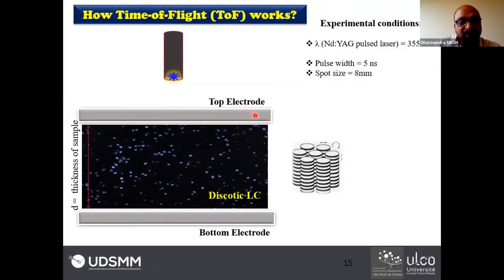Basically, what we do is place these discotic liquid crystals in between the top electrode and bottom electrode. In order to fix the thickness, we put in a spacer so that the thickness between the top electrode and bottom electrode is fixed. We fill this material at isotropic temperature with a very slow cooling rate, so that the molecules are perfectly arranged in the homeotropic way. Homeotropic means all the molecules are perpendicular to the bottom electrode. So the charge transport will go this way.